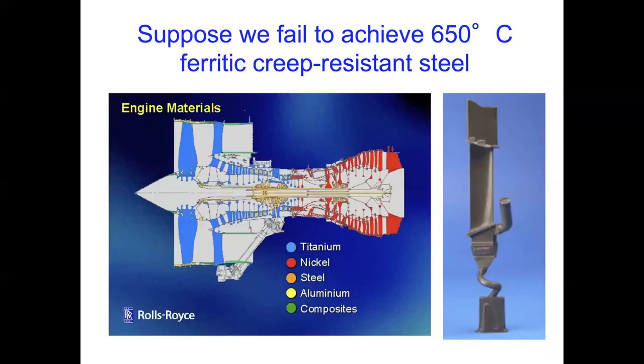As Hong Biao knows, in the jet engine, the highest operating temperature is in excess of 1400 degrees centigrade, which is higher than the melting temperature of the nickel-based superalloy that you put into that region. So it's protected by various coatings and cooling channels.